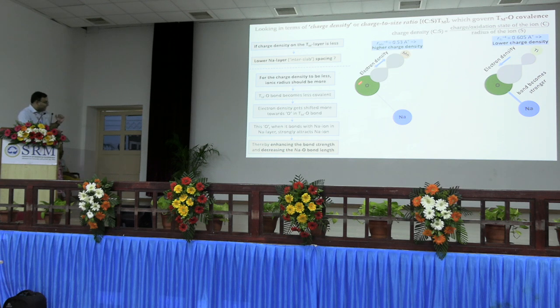No, but in this structure, it is the same oxygen ion which on the other side is bonded to a transition metal ion, which is ionocovalent. So we can actually do a lot with that by tuning the covalency of the transition metal oxygen bond.